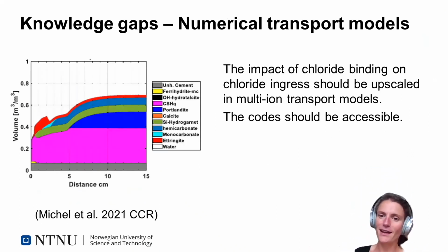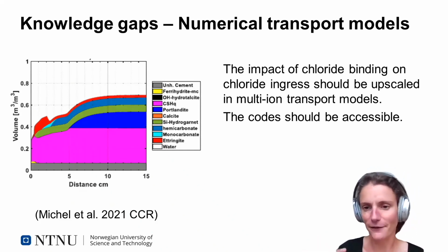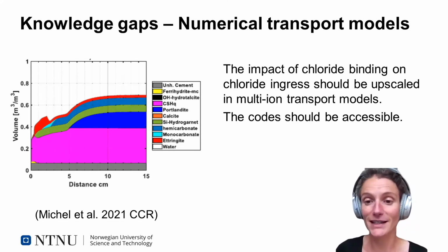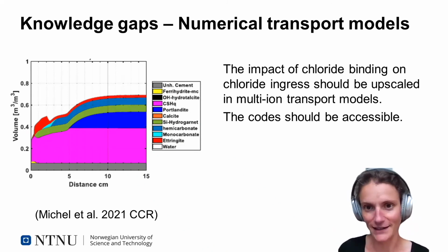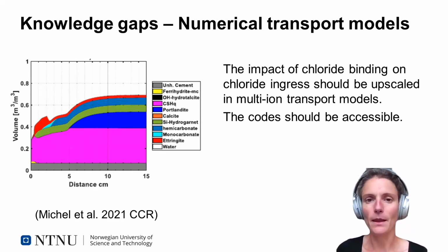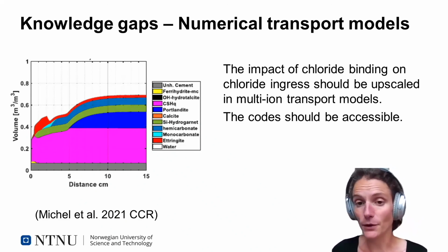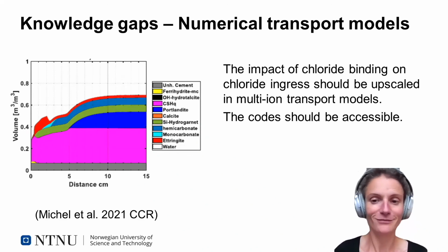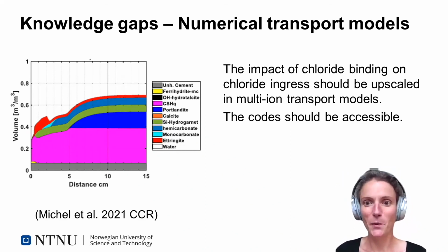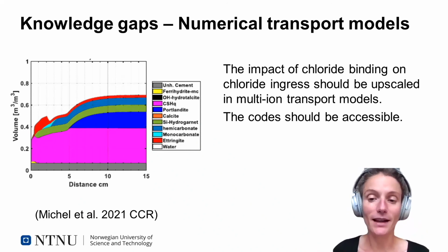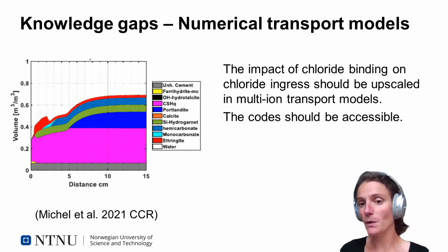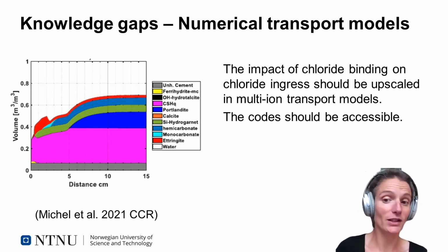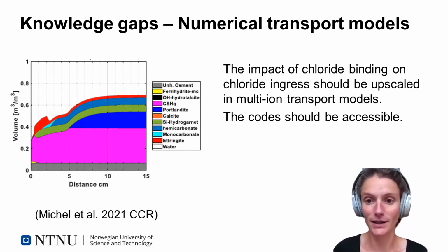Now, if we have a better grip on our AFm and similar phases and on our CSH and are able to predict chloride binding in these phases, this should be included in numerical transport models. There's an example here of a recent one published by Michel, but there's a handful of good multi-ion transport models. For more information, look at the paper. One thing I would like to say here is that it's important that these codes are made accessible so people working with binding can contribute, and the engineer responsible for his bridge can look into it and try to see what he can use. So we need to work together with transport modelers.